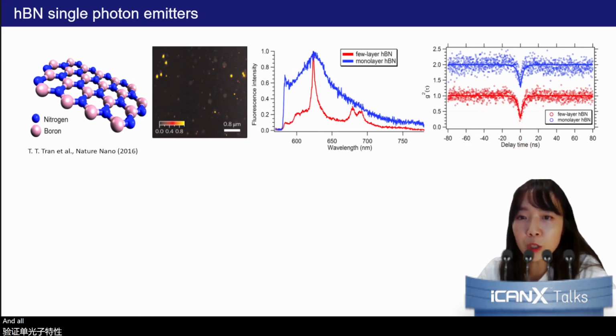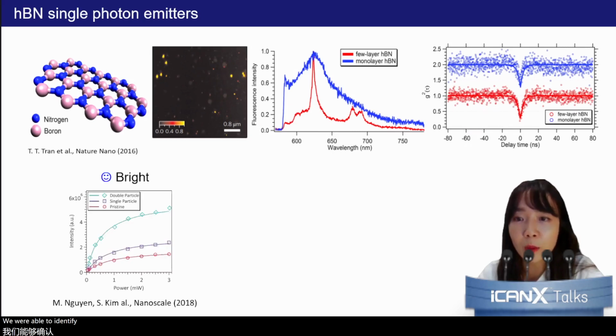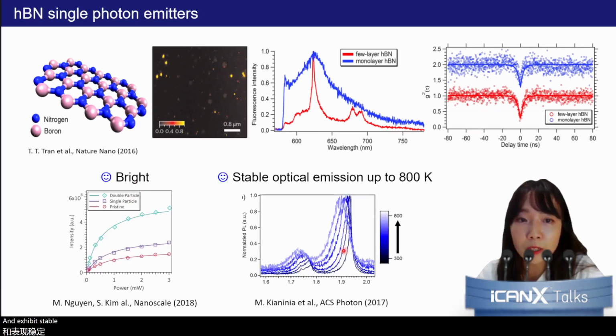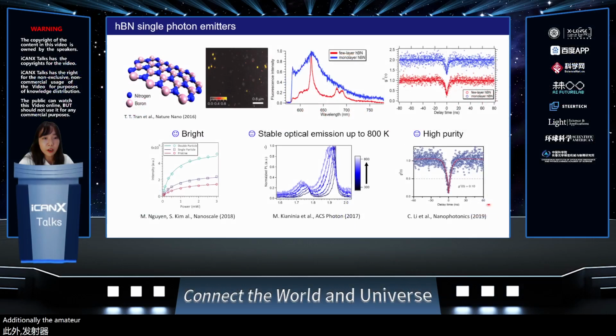Although this new quantum emitter was discovered relatively recently, we were able to identify a number of favorable features. For example, HBN single photon emitters are very bright and exhibit stable optical emission, even up to 800 Kelvin. Additionally, the emitter shows a high degree of purity, implying that the probability of observing multiple photons is extremely low.